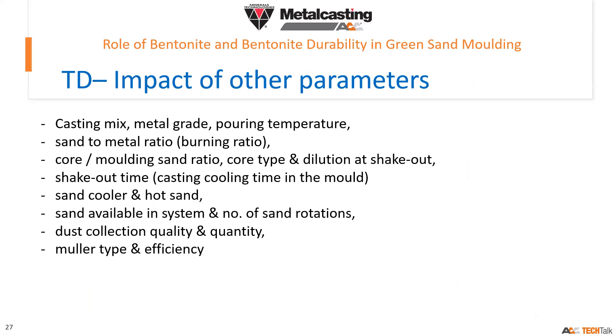At this stage, what we must keep in mind is that whether it is TGA analysis, MBV, or thermal durability analysis, we are not considering many aspects of running a foundry — like casting mix. When there is a change in casting mix, your metal grade will change, your pouring temperature will change, your sand-to-metal ratio will change, and that will affect the burn ratio.